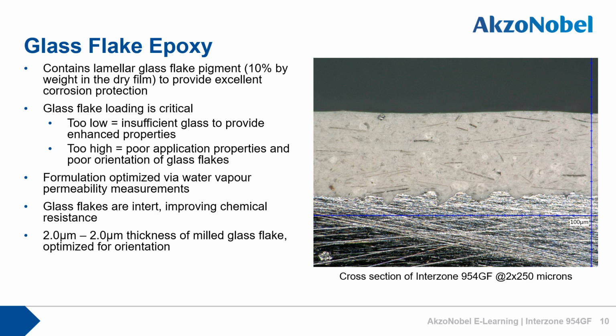On the other hand, if you go too high, then you lose out on the application properties of the product, as there isn't enough resin to be able to flow out and wet the substrate well. Over the years, we've found that 10% glass flake content provides the optimal balance between the two. And in this way, we've been able to retain all of the excellent characteristics of the original 954 with the added benefit of enhanced corrosion and abrasion resistance from the glass flake loading.